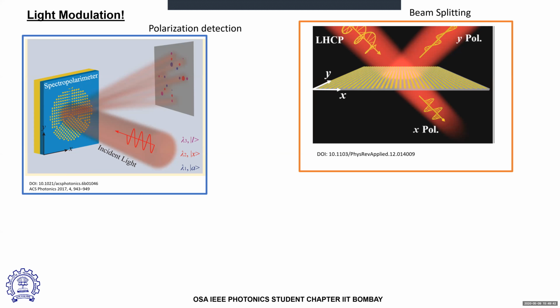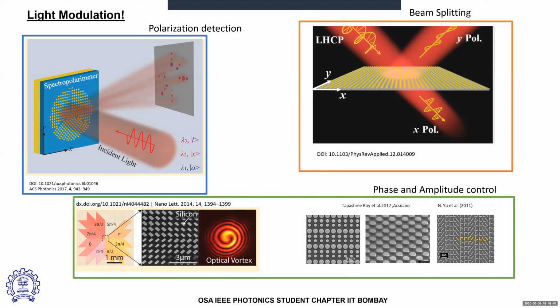Then we can also have some phase and amplitude control together, where we try to pattern small structures in different orientations. These orientations introduce a phase gradient into the reflected beam of light, and this phase gradient can be designed according to the orientation and the size of the nano antenna. So here in the left bottom image, you can see the silicon patterning, where the orientation and thickness introduce different kinds of phases into the incident beam, and then in the reflected form we find an optical vortex with the intensity varying from the center to the edge of the vortex.